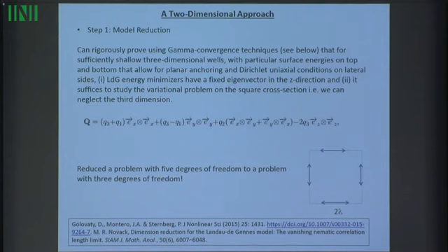And once you have all these reductions, you've gone from a 3D domain to effectively just a square. You can now neglect derivatives in the Z direction, and you are restricting yourself to Q tensors which have one fixed eigenvector. You've gone from your Q tensor, which has 5 degrees of freedom, to an object which now only has 3 degrees of freedom. So there's already some model reduction here. You're studying a simpler problem. Well, it's not necessarily simpler, but it's certainly reduced in this thin film limit.